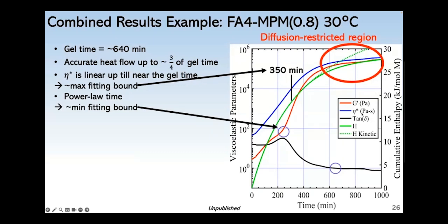So the raw enthalpy, or the enthalpy after it's been shifted and corrected, and then the predicted enthalpy from the fitting equation, which is the H kinetic. And it's not until about 3/4 of the way to the gel time where the predicted enthalpy splits off from the measured enthalpy. And I interpreted this as diffusion restriction that comes with forming a gel.